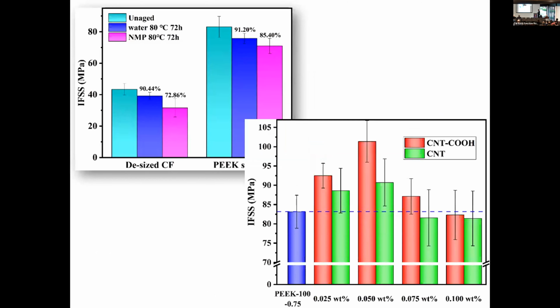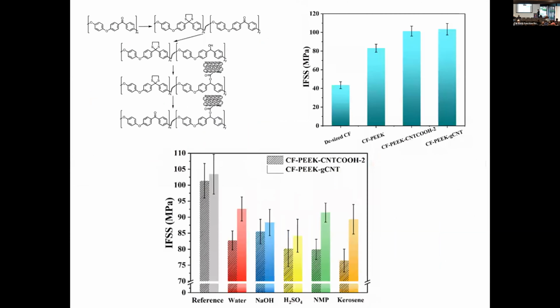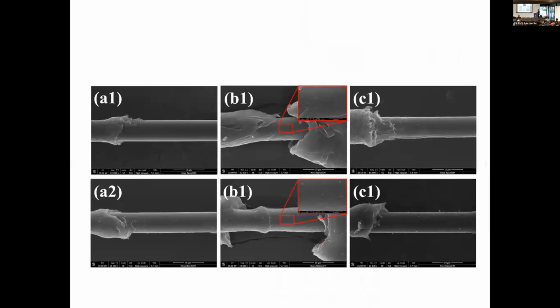And then further, we added carbon nanotubes into the sizing agent, so you further increase the strength. Also, if you do some treatment of the carbon fiber, here with acetylene, you can make the carbon nanotubes more ready to distribute and avoid agglomeration. So you further increase the strength, and then you even do the grafting of PEEK onto the carbon nanotubes. Then we look at the mechanisms.